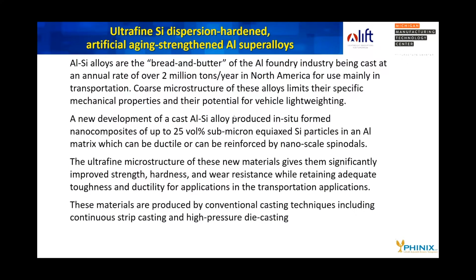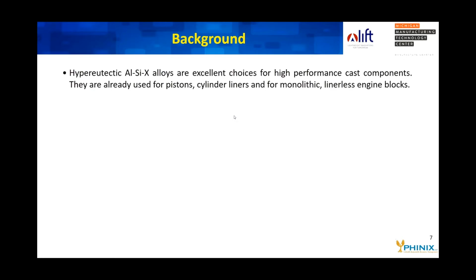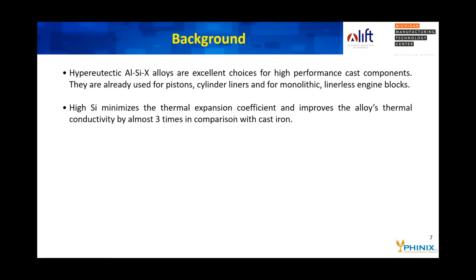Some background: the hypereutectic aluminum silicon alloys with other additives are excellent choices for high-performance cast components. They are already used for pistons, cylinder liners, and for monolithic linerless engine blocks. The high silicon minimizes the thermal expansion coefficient, and improves the alloy's thermal conductivity by almost 3 times in comparison with cast iron.